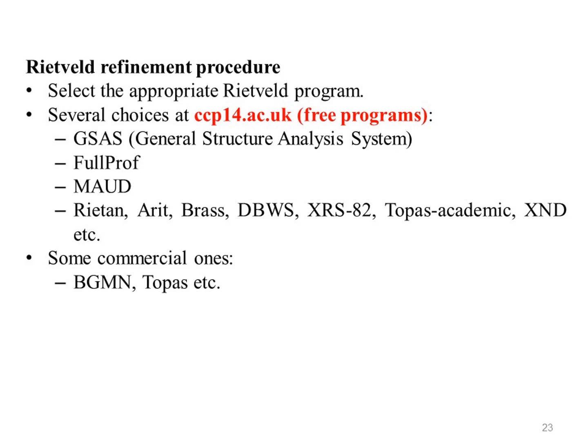First, GSAS, General Structure Analysis System. Most used, very good for crystal structure refinement, and TOF neutron. Not easy to use, but there is a lot of knowledge around. A friendly graphical interface is available with EXPGUI. FullProf, best for magnetic materials, good for crystal structure refinements. No graphical interface in preparation. MAUD for material scientists, good for quantitative phase analysis, size, strain and texture, best in the case of texture and strain problems, comes with a graphical user interface.